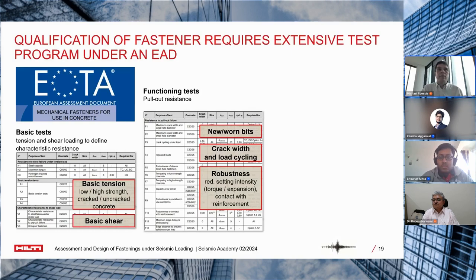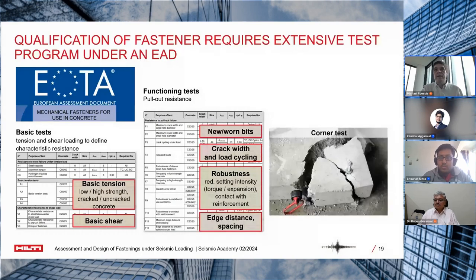We need to do some crack cycling tests also for static loading because our concrete elements may develop cracks during the lifetime and those cracks may vary a little bit. And we check the robustness of those products. And we do tests, for example, for edge distance and spacing just to avoid situations that anchors installed on a job site create failures like we see here on that photo.